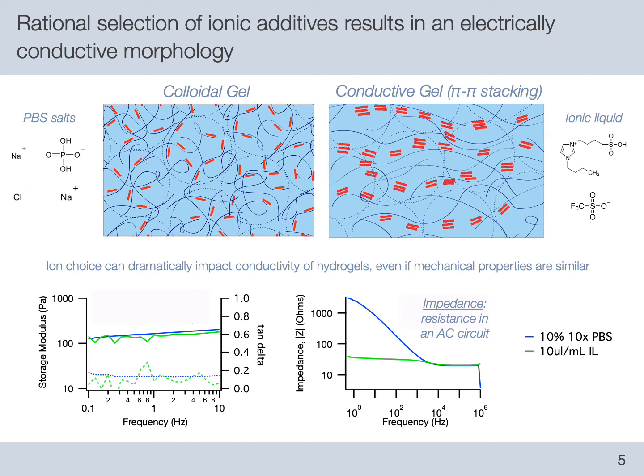on the bottom right. This transition from a highly frequency-dependent impedance to one that stays relatively low and flat is also consistent with the transition from an ionically conductive material to a material that can conduct electrical charges at low frequencies as well. Thus, we argue that these ionic species transform PEDOT:PSS from a colloidal gel to a conductive gel with an extended pi-pi stacking-based conductive network.